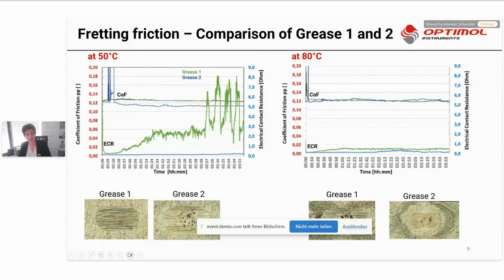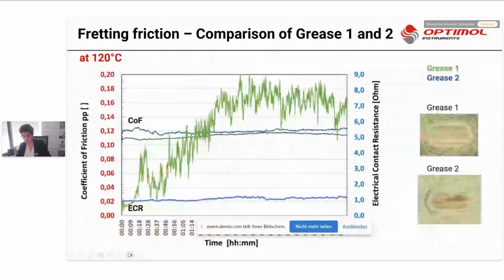Looking at the wear scar on these two greases, grease 1 with higher electrical contact resistance has much better fretting protection than grease 2. At 80 degrees, very interesting. It's also mentioned, for those who are in the field of tribochemistry, that the tribofilm composition always changes between the different temperatures. Coefficient of friction is rather the same, but here we don't have a high electrical contact resistance for grease number 1 in both cases, and not a good fretting protection.